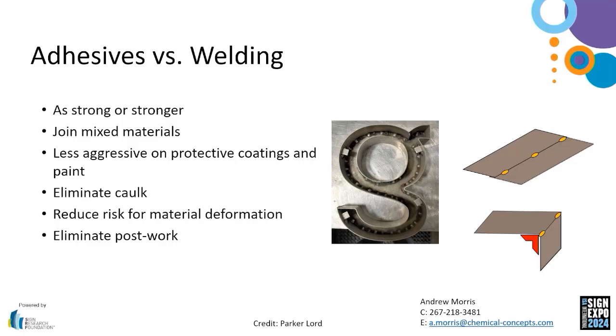And so one of the things that adhesives can do is they can spread the load over a larger area. When you have spot welds, you're typically doing pinpoint spot welds, hence the word spot, and that is stress concentration. All of the load applied when the wind comes, or if it's a machine pulling these apart, gets concentrated on pieces of metal. The metal starts to deform in those areas, they become weak points, cracks propagate, and then you have a failure. So when you compare 12 inches of spot weld to 12 inches of continuous adhesive with a 2-inch overlap joint, and an adhesive that's, say, 2,000 PSI multiplied by the surface area of a 2-inch by 12-inch strip, now you got a lot of force capacity.